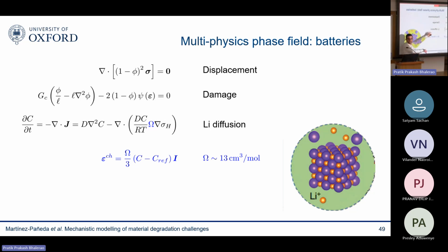So we had it in the hydrogen model as well. It just becomes negligible because your model depends on physical properties. So you have this partial molar volume that is a quantity that we know, that we have measured independently, decades ago, that is well established. So when you have this kind of physical model, you don't need to make any assumptions on what the physics happening is. You just put the real parameter values and the model will tell you what's happening.